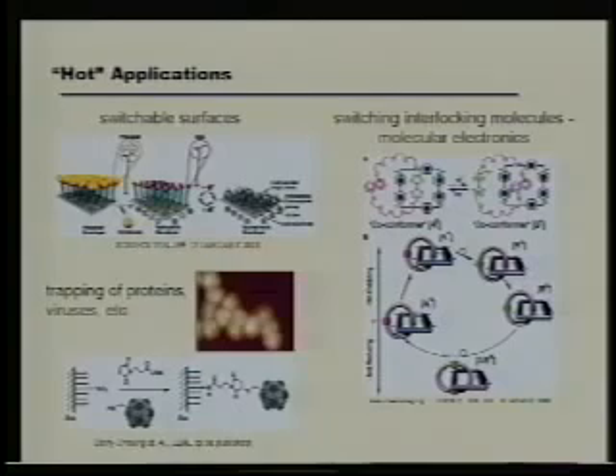There's actually numerous, what I'm going to call hot applications for these type of materials. There's been a recent paper that shows you can actually get switchable self-assembled monolayers where they stand up and are hydrophilic, and then if you remove one of the groups, they'll actually bend over and you'll get a hydrophobic surface. So you can switch it from a water-loving to a water-repelling surface with just changing a little bit of surface chemistry.